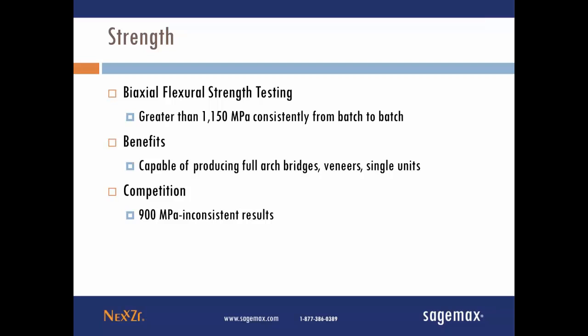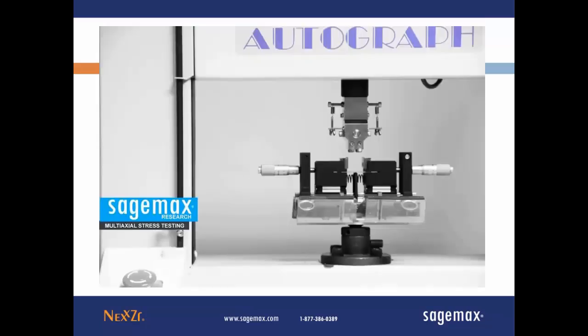The benefit is that we are capable of producing large bridges, veneers, as well as single units. Our competition shows that sometimes it's even below 900 megapascals. Sometimes very inconsistent results that we show by doing comparative testing. And here's an image of our actual biaxial flexural strength testing. And if you go on our website, there is a video up online where you can actually see the test being performed. You may want to ask, why do we perform all these tests? Our goal is to provide a very consistent material from batch to batch. And this is why we painstakingly do a lot of these tests in-house.